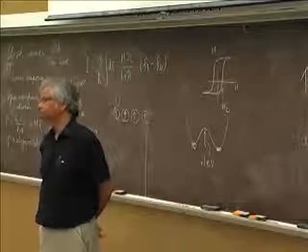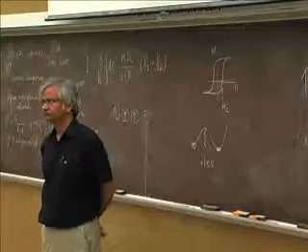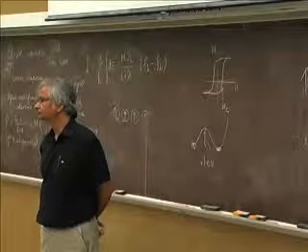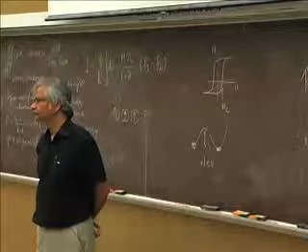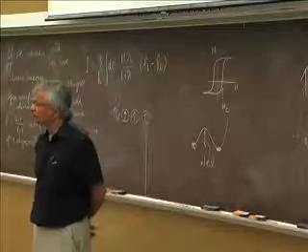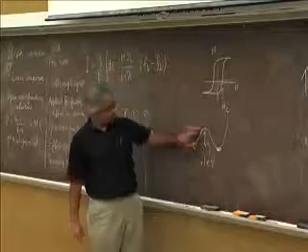Why did you raise this question? Because we are doing our own simulation. In our own simulator, I haven't done a theoretical, analytical model, but we have found that if the thickness is 1 nanometer to 2 nanometer, and the nanomagnet's aspect ratio is 100 to 60 or 100 to 70, it flips with the thermal noise. Oh, I see. Okay, so a lot will depend on whether the parameters you used correspond to what barrier.